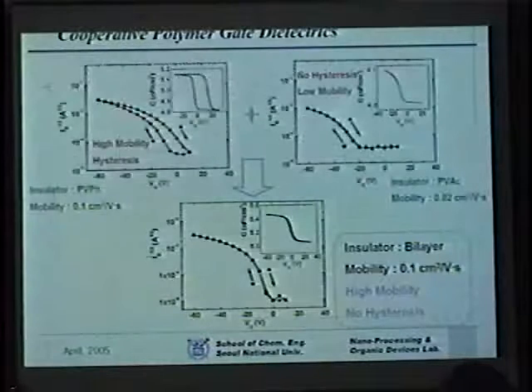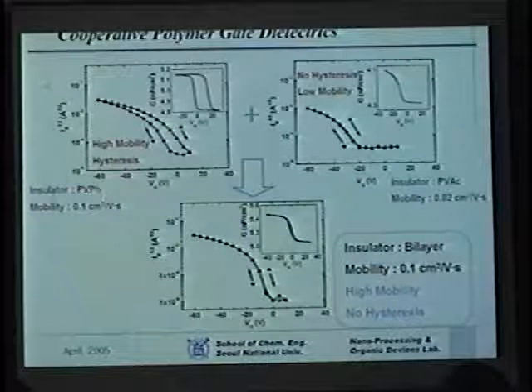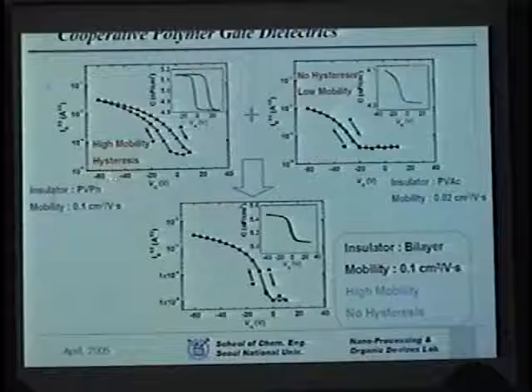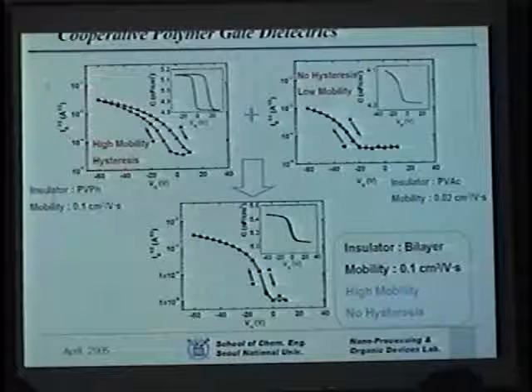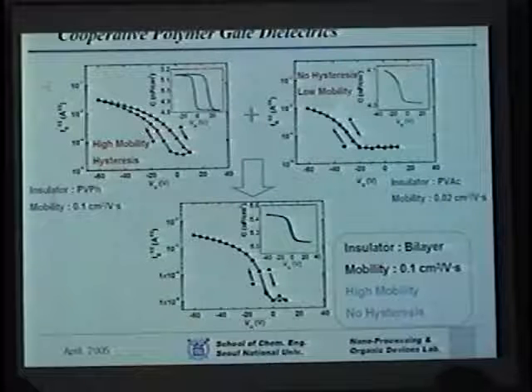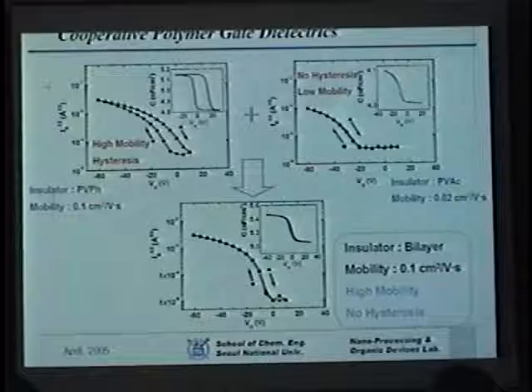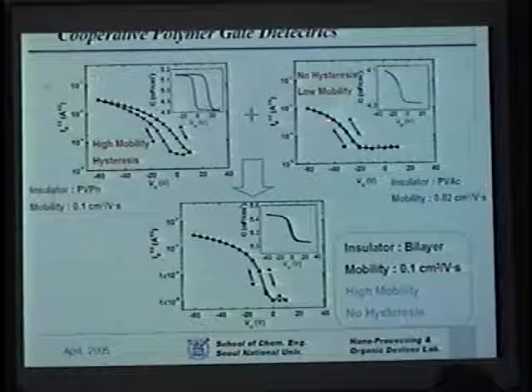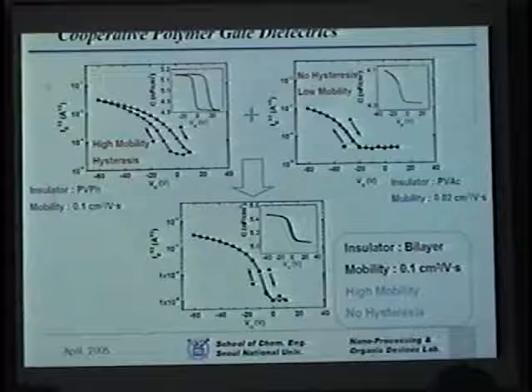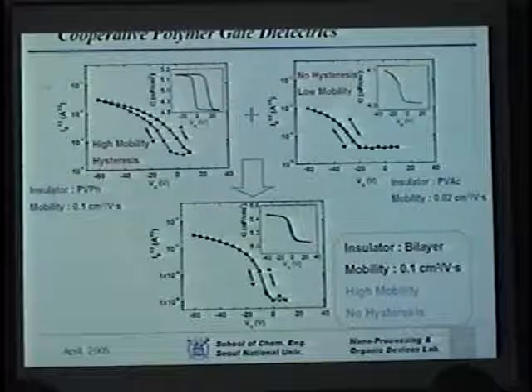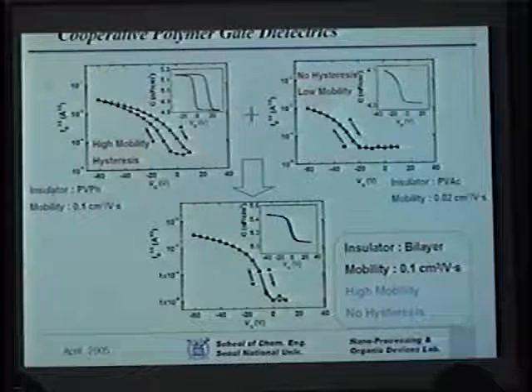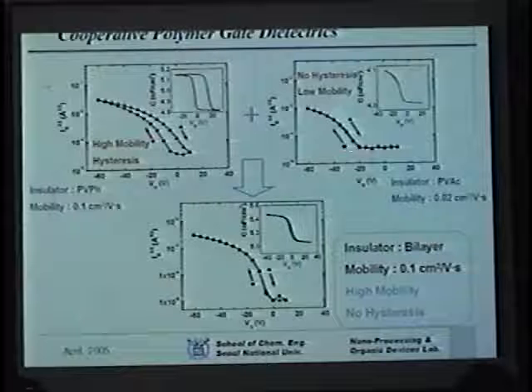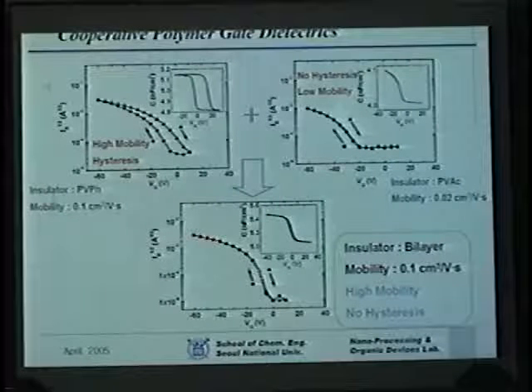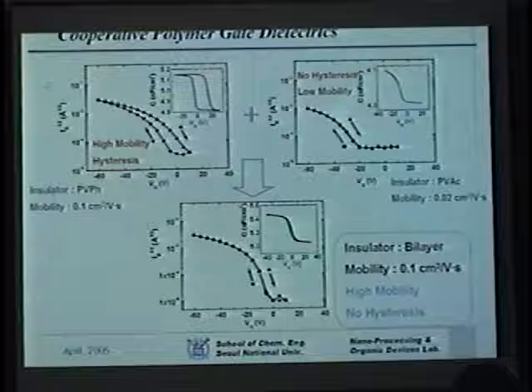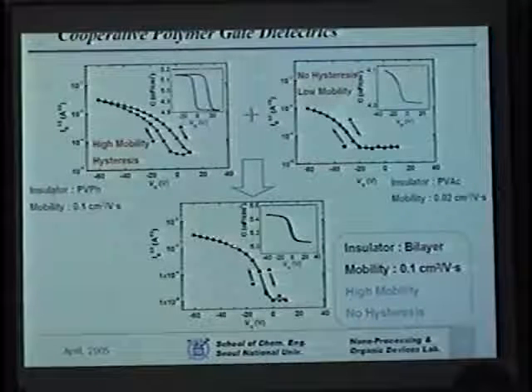to eliminate the hysteresis problem. And as you can see, when we use PVPH as the gate dielectric, you get high mobility, but you do have this undesired hysteresis problem. As you can see, mobility is about 0.1. Whereas with the other, you do not have any hysteresis at all, but the mobility is fairly low, a typical value. But when you have the kind of bilayer that I talked about, you can combine this high mobility with no hysteresis, which means no threshold voltage shift, and you can have satisfactory mobility as well.